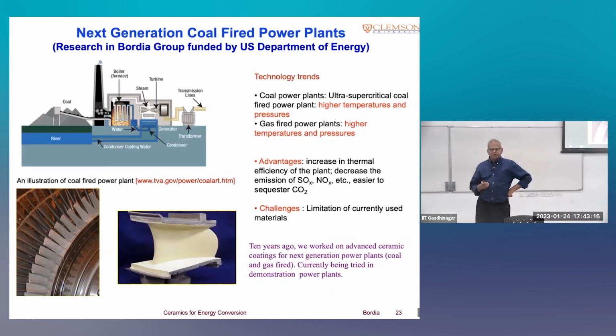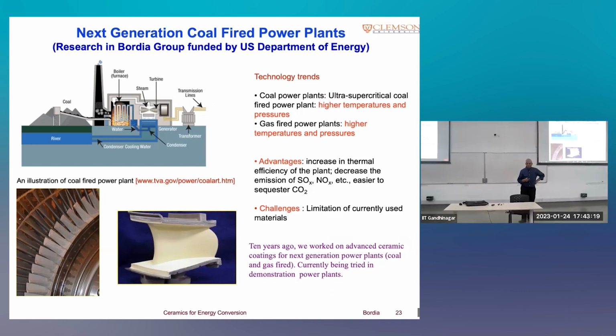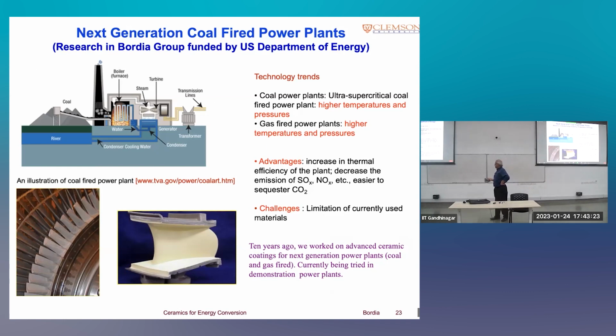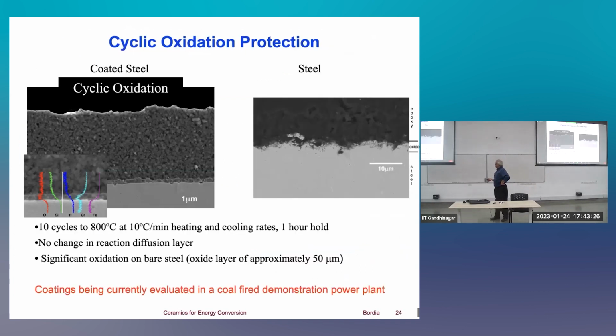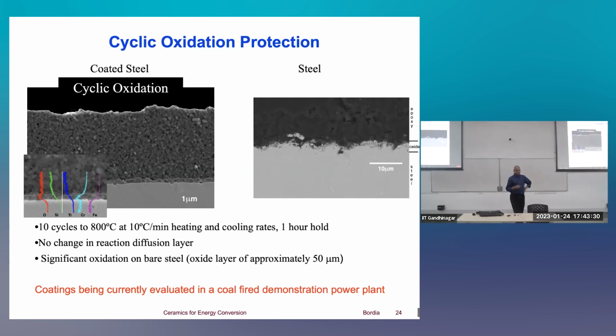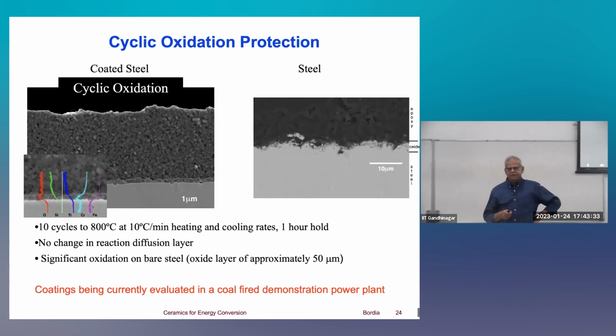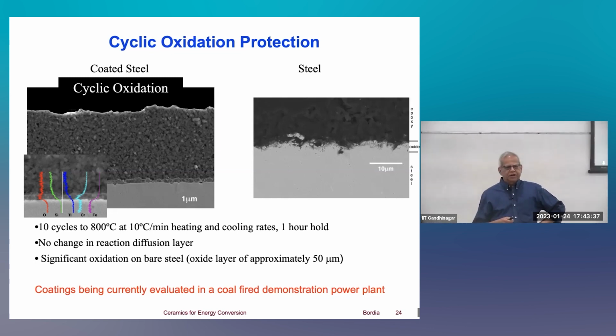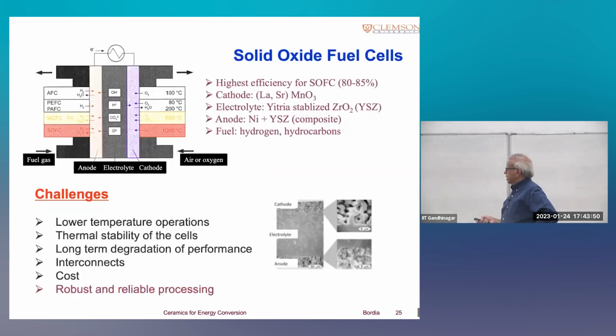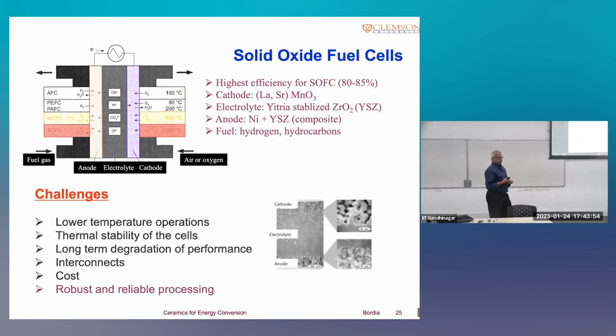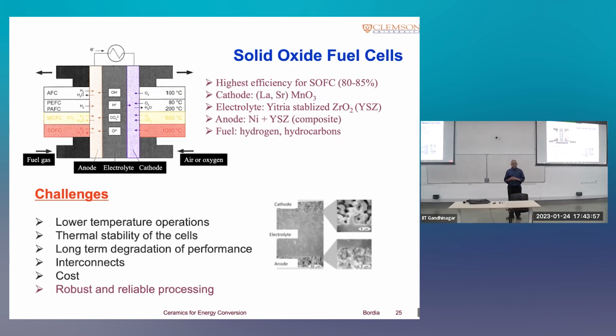So here are some examples of the work that we have done over the years on improving the efficiency of classical thermal power plants, from coal-fired power plants to gas turbines. We've been working on developing these ceramic coatings on metallic systems that let us go to higher temperatures. In the case of turbines, the improvement is roughly about 150 to 200 degrees C by using about 150 micron thick coatings of ceramics. So the second area that we have been working on in my group is solid oxide fuel cells. These are electrochemical devices that convert chemical fuels like methane, for example, directly to electricity without burning it.